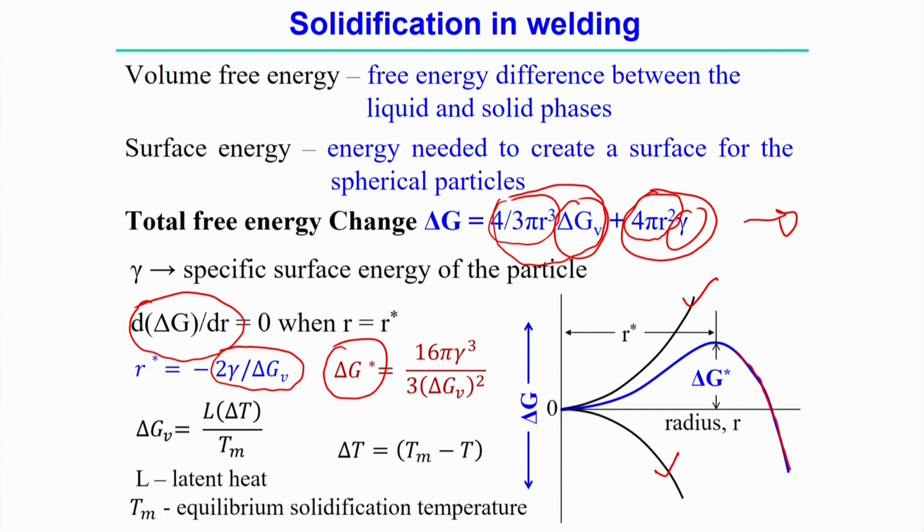It is 2 times the ratio of the specific surface energy and the volume free energy, related to the change from the liquid to the solid phase.